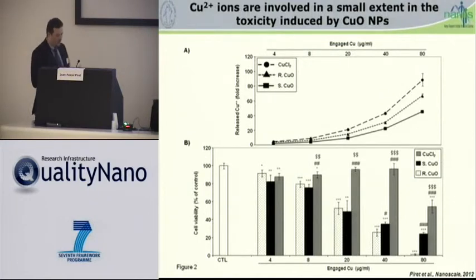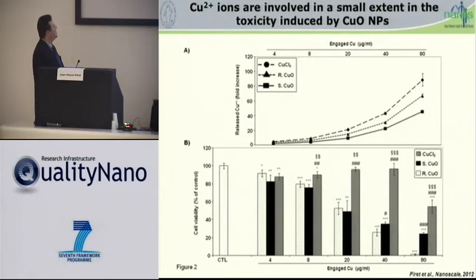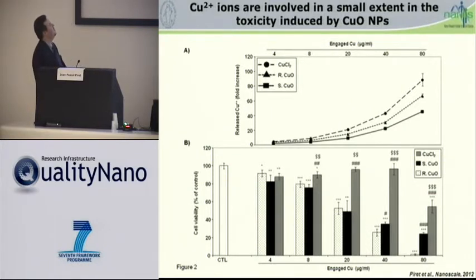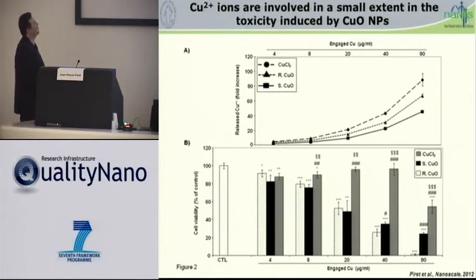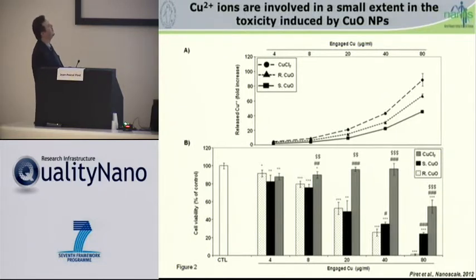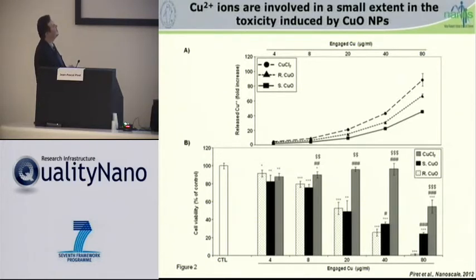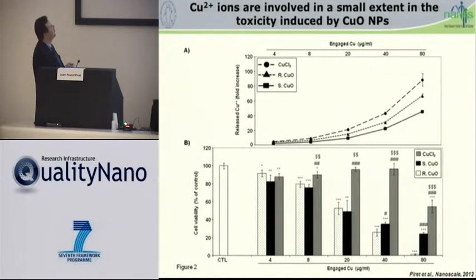Next, we wanted to know whether these nanoparticles could induce toxic effects on HepG2 cells, and whether release of copper ions could participate in the toxicity. Firstly, we measured the release of copper ions from both copper oxide nanoparticles and compared to the copper chloride salt. We observed a dose-dependent increase in the release of copper ions from both nanoparticles, with higher release from rod-shaped nanoparticles in comparison with spherical nanoparticles.